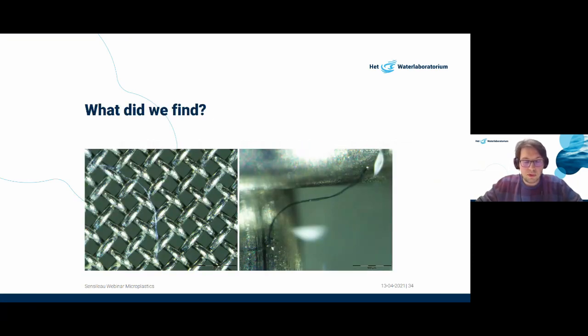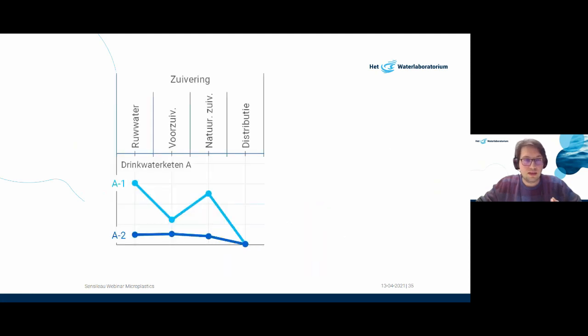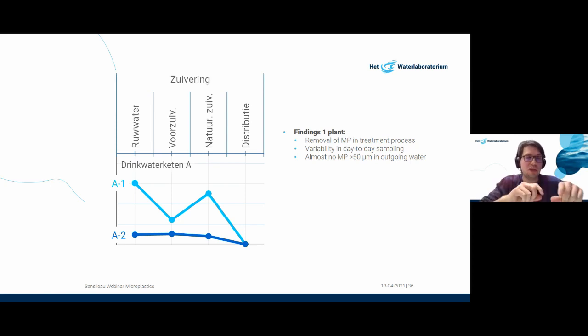So perhaps what everyone has been waiting for so far is, what did we find? Well, of course we found microplastics, because that's what we're looking for. But we did find some things that are quite interesting to discuss. If we looked at the purification efforts, the first thing we noticed is there's a very large variability from day to day. The amount of microplastics you find on day 1 and day 2 can really differ significantly. What we also saw was a general trend that during water treatment, so the different treatment steps in drinking water production, the amount of microplastics steadily decreased.